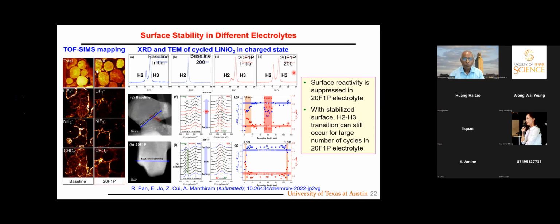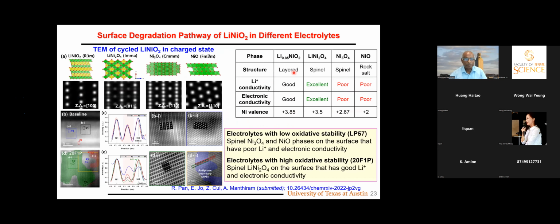So overall, surface reactivity is the dominant issue that has consequences for cracking, rather than the cracking itself. Or in other words, if you have a good electrolyte, you can try to overcome the problems with the cracking. That's what I'm trying to say.